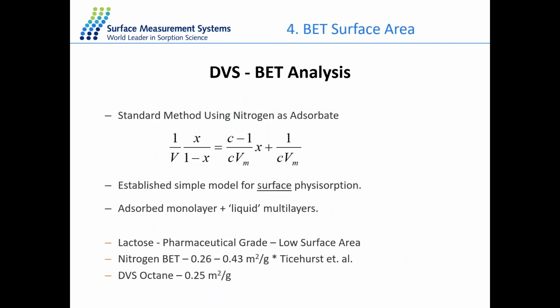And the next application quite relevant to pharmaceutical applications is the BET surface area determination. And the theory we use here is exactly the same as the volumetric technique with nitrogen sorption. So we can measure the amount of vapor adsorbed by the surface and also the vapor pressure above the surface. And then we can fit the line to get the monolayer volume and the sorption constant. And with the cross-sectional area of the probe molecule we are using, we can then calculate the BET surface area of the material.